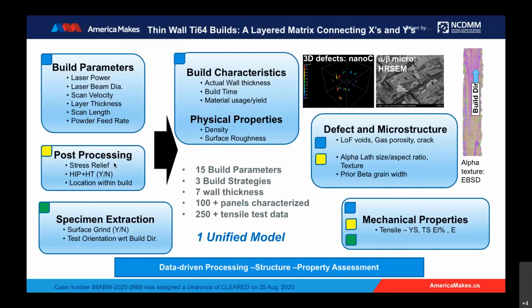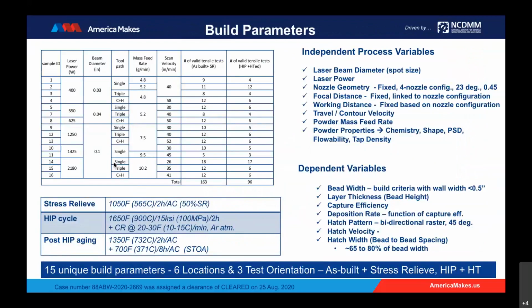So let's talk about the DOE for feature 1 here. So you can see that what we executed in this particular feature, we had a wide range of parameters intentionally developed, ranging from a power setting of about 400 watts to 2 kilowatts, tool paths being single to triple to C+H's. We kept some of the parameters constant to have a manageable DOE. Things like nozzle geometries and focal distances were kept constant, where obviously speeds and feeds are going to change based on the beam diameters and the power that you use.